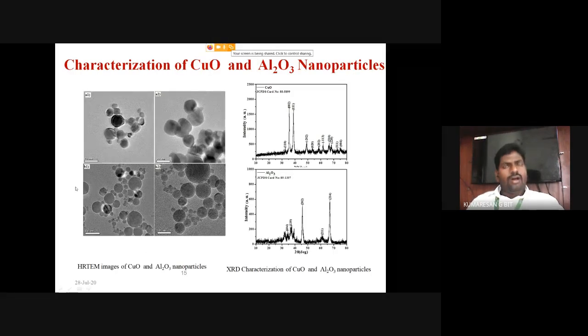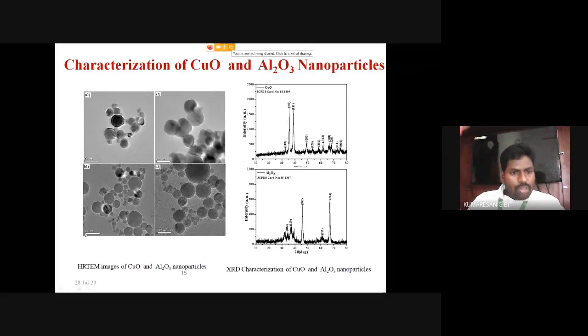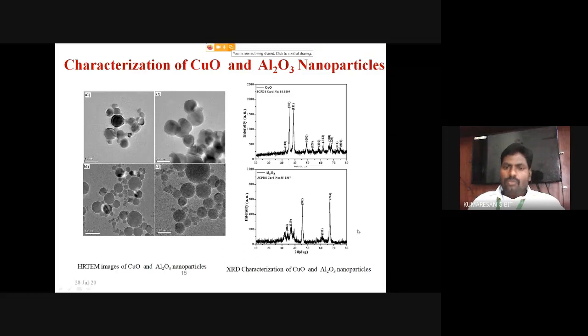Then the next one is the characterization of the prepared nanofluids. First, HRTEM and XRD characterization methods are performed to finalize the size and morphology of the nanoparticles. First, HRTEM images of CuO and Al2O3 nanoparticles are shown in figure 1. So here you see both CuO and Al2O3 nanoparticles are spherical in shape, and the nanoparticle size is 30 to 40 or sometimes up to 50 nanometer. And XRD analysis also takes place to finalize the size of the nanoparticles by using the Scherrer formula. Okay, here the size of the copper oxide nanoparticle is confirmed at 39.1 nanometer, and for the aluminum oxide nanoparticles it varies from 40 to 50 nanometer, but both are nearly the same.